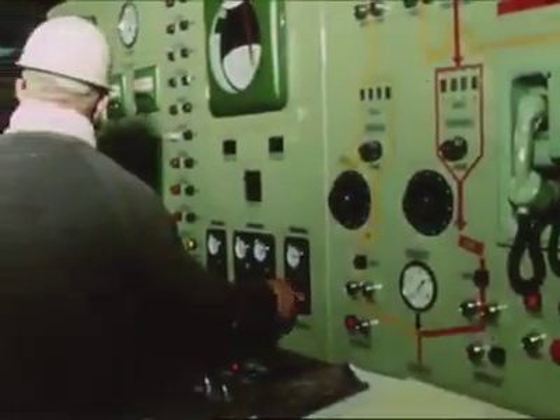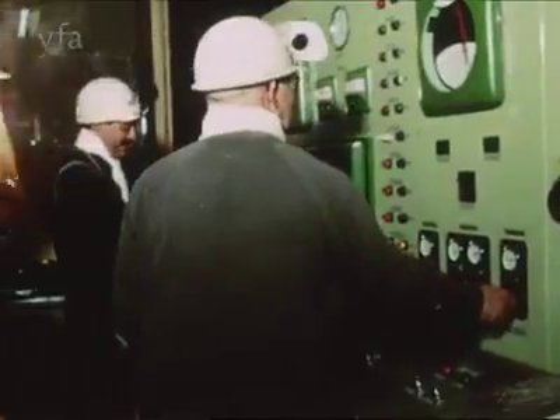The vessel is tilted into its inclined operating position, the fume exhaust hood swung into place and the vessel rotated. Oxygen is then blown in at a predetermined rate. The oxygen removes the silicon, manganese, carbon and phosphorus impurities and raises the metal temperature. When the calculated amount of oxygen has been blown, the blast is turned off and the hood swung aside. All operations are controlled from a pulpit alongside the furnace.